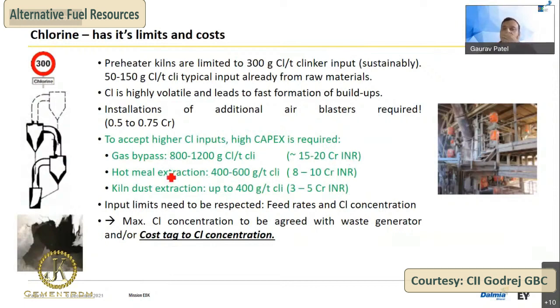There is also hot meal extraction, which will give only an additional potential of 200 grams increase of chloride, by extracting material around 1 to 2 tons per hour from the bottom stage cyclone hot meal. So this way we can increase the chlorine potential by 200 grams. Another is kiln dust extraction: in the direct mode of operation, whenever the raw mill is off, we extract the gases from the baghouse and don't mix them into the homogenization silo. This will also give around 100 grams of chlorine potential increase.